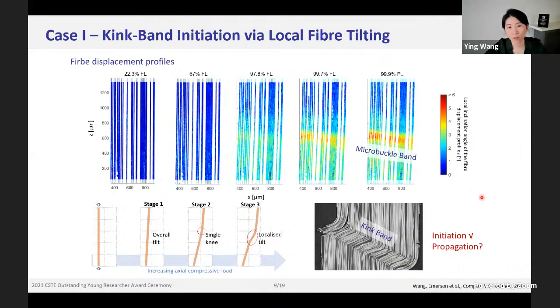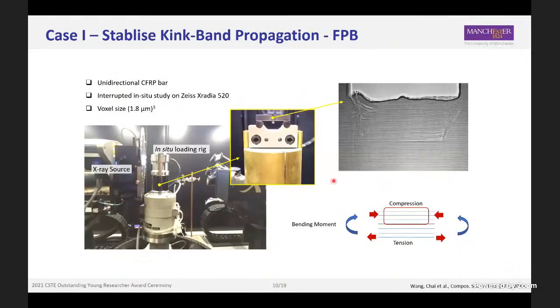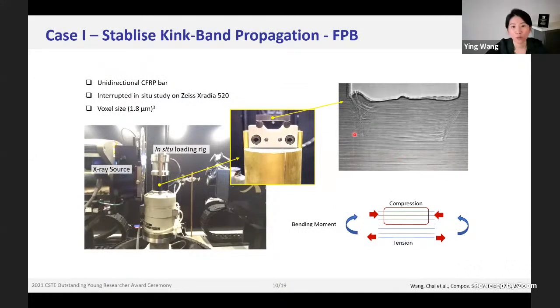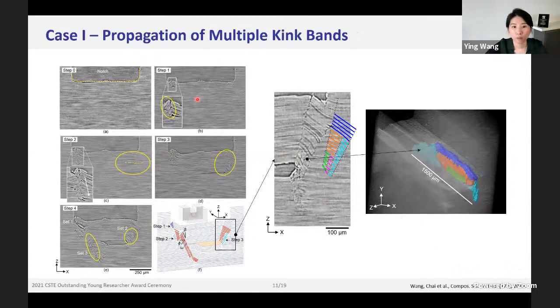So talking about initiation, we are still interested in the propagation as well. So we designed an experiment to include 4-point bending moment to stabilize the kink band propagation. And in this case, we managed to monitor the development of multiple kink bands in the composite. And with the 3-dimensional capability of X-ray CT, we can not only see the propagation damage mechanisms in the kinking plane, we can also see the propagation mechanisms transverse to the kinking plane in the third dimension.